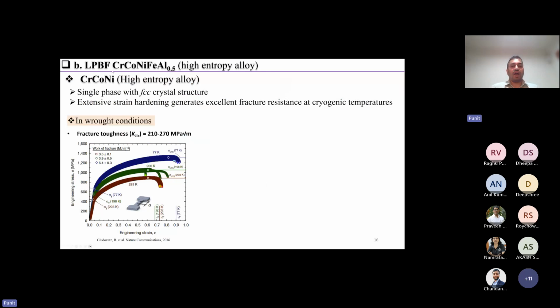So coming to the second alloy of this part, we wanted to look through this. The idea of this project was to investigate a composition similar to chromium cobalt nickel, and the idea of this project came through this thought process that I want to talk about. So chromium cobalt nickel is a high entropy alloy which has a single phase FCC crystal structure, and it shows extensive strain hardening, which generates excellent fracture resistance. And even at cryogenic temperature, the extent of strain hardening further increases. Because of that, you have a fracture toughness that ranges from 210 to 270 megapascal root meter.